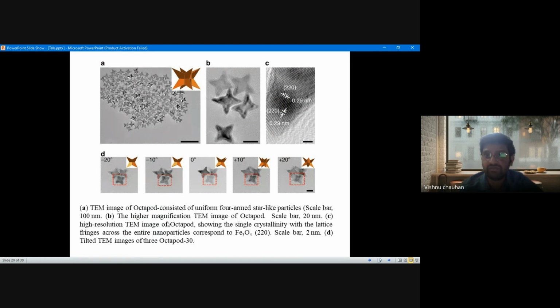Further, if we go for more analysis, we can obtain the lattice parameters also. We can determine which plane we have. We have the 2 2 0 plane, and the specific interplanar spacing between the atoms. Here we can see we have 0.29 nanometers. So we can say how specific and how deep an analysis we obtain from the TEM micrographs. We can rotate the material at any angle, minus 20 degrees, minus 10 degrees, 0, 10, 20, or any other.